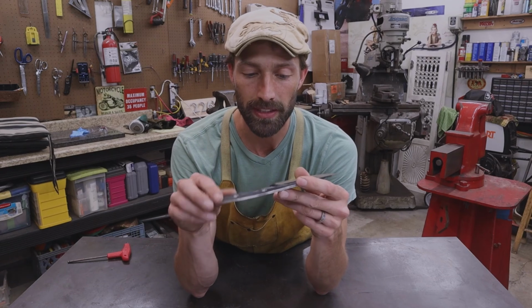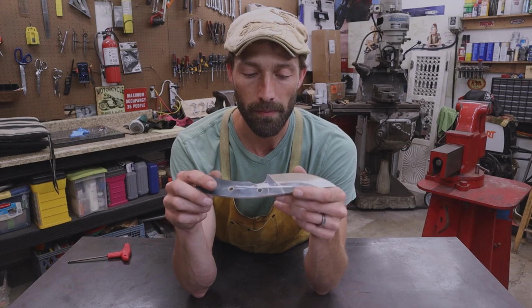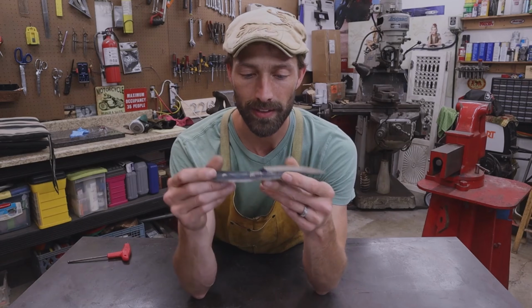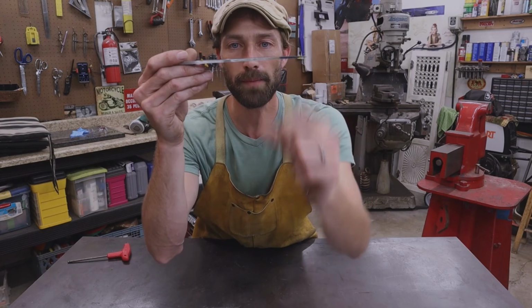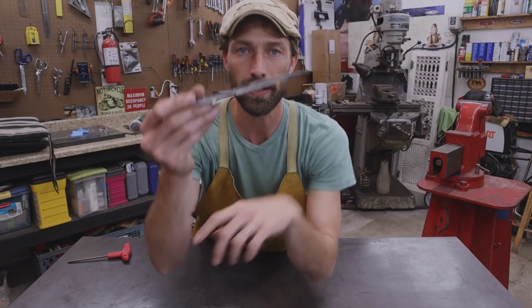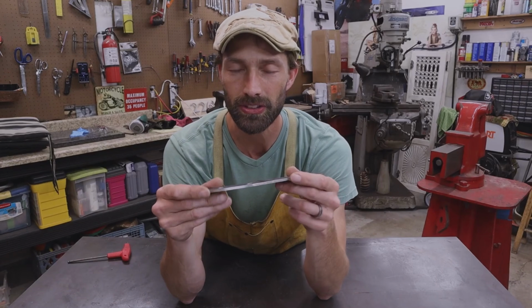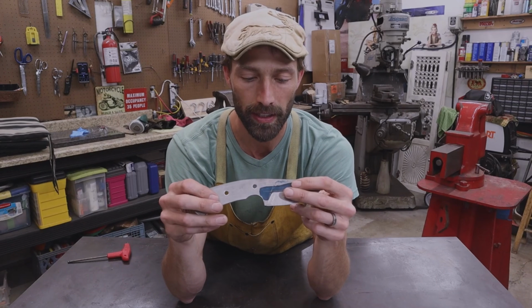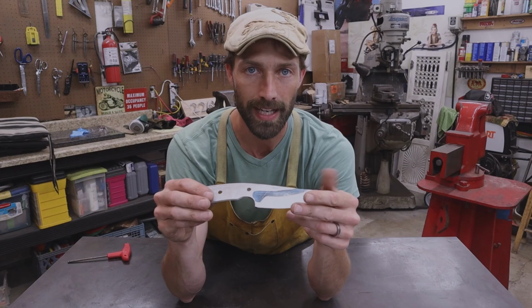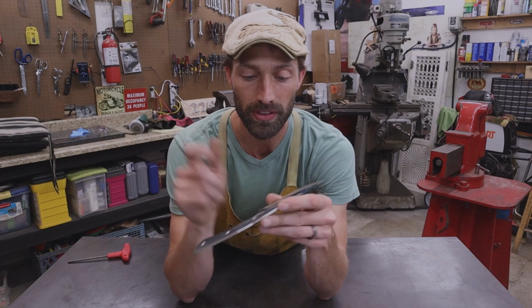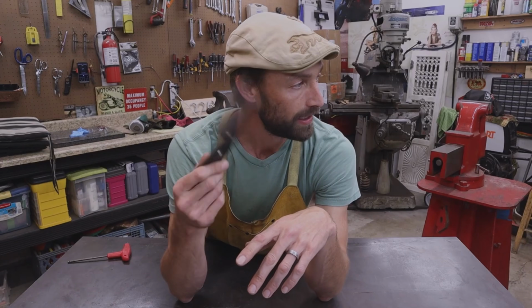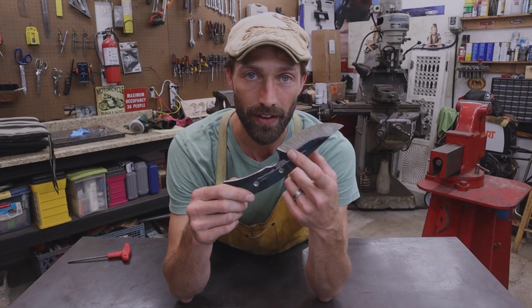I used to stamp these while they were hot. But the problem I found with that is if you lay it flat and you stamp it while it's hot, it kind of bends the blade both directions, and then it started to introduce warps into my blades from that hot stamping. So I stopped doing that. Now I cold stamp the metal and then I heat treat it, and it works great every time. So I'm gonna go ahead and show you how I stamp it.